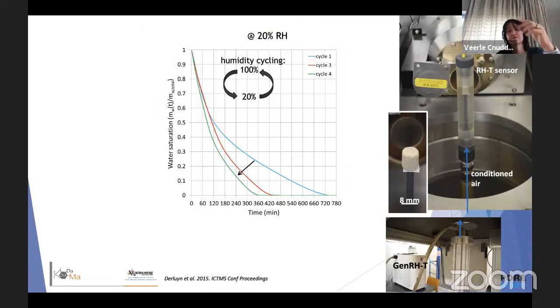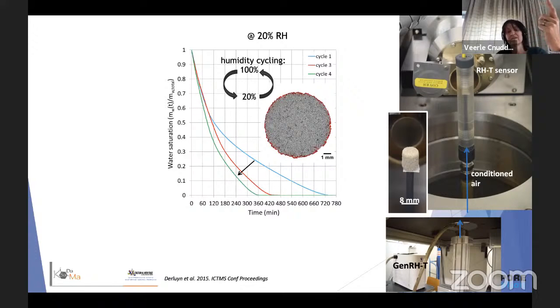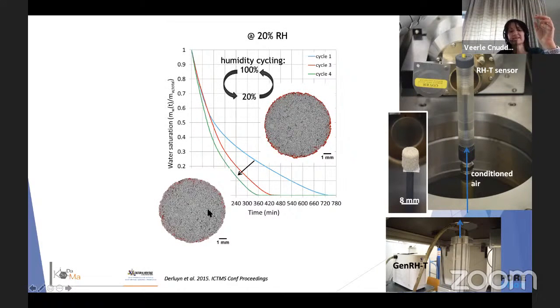Because it's non-destructive, you can repeat it. You can make your sample wet again and dry it again and see how the salt is migrating. If you do cycles of wetting and drying, after a few cycles you'll see that the salt is not at the surface anymore, but is precipitating more internally in the rock, which might be a problem, because salt precipitating at the surface causes aesthetical problems, while salt precipitating inside the rock can create pressure zones and create fractures and degradation.